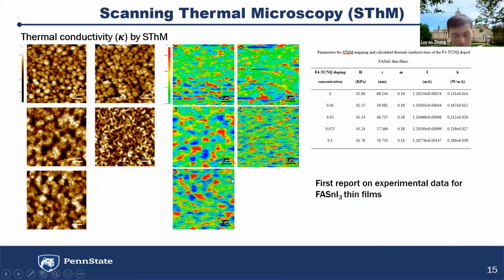And here's the result. The first 5 figures are the AFM mapping images of the thin film, while the latter 5 are the current mapping during the AFM measurement. We can obtain all the parameters from the measurement. For different concentrations of doping, we get a different average probe current from this mapping. And overall, we can calculate the thermal conductivity depending on the equation we show here, equation 9.